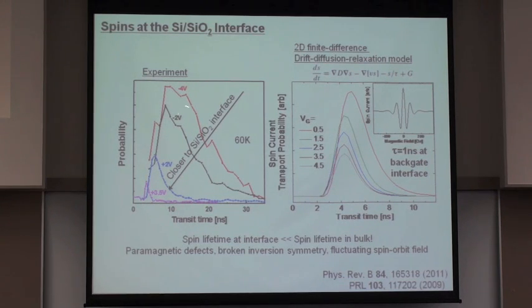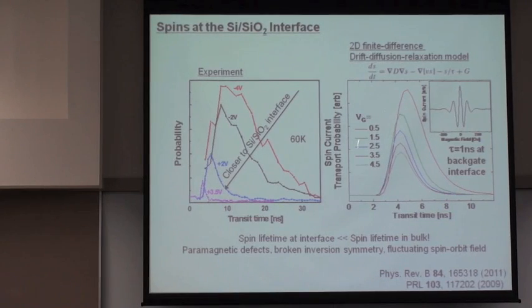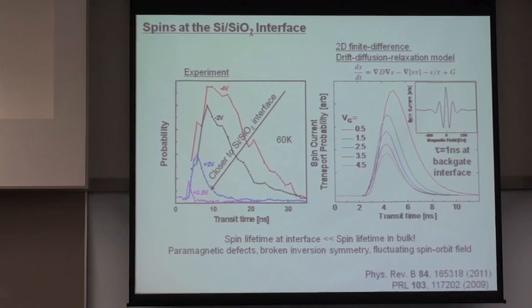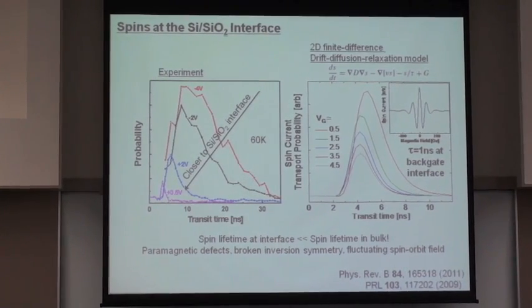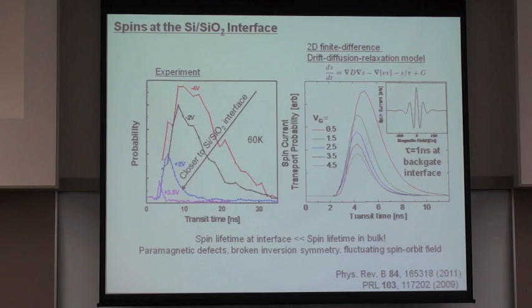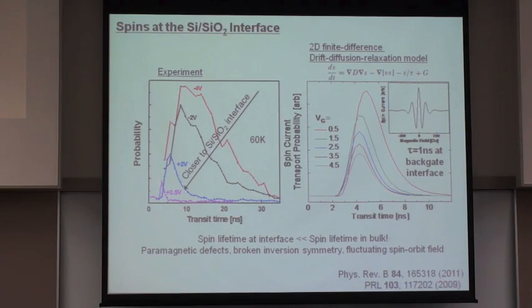So basically what this shows here are the spin current transport distributions under the influence of the gate voltages that you see here. With more positive gate voltages, we're pulling electrons closer to that interface, and we see a depolarization, which gives rise also to an apparent shortening of the transit time. And this has been recently modeled using two-dimensional finite differences, in which we can say that the interfacial spin lifetime is actually orders of magnitude shorter than the bulk spin lifetime that we've seen in vertical transport devices. So it's a very strong effect that we can control with the application of electric field in this lateral transport geometry.